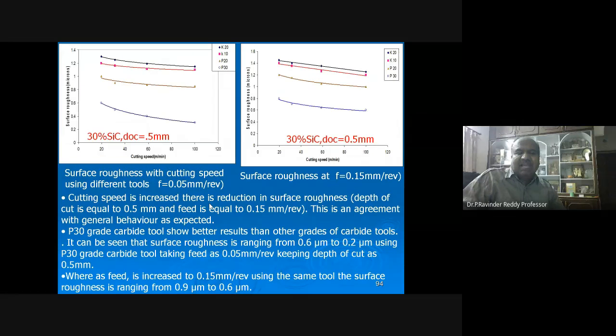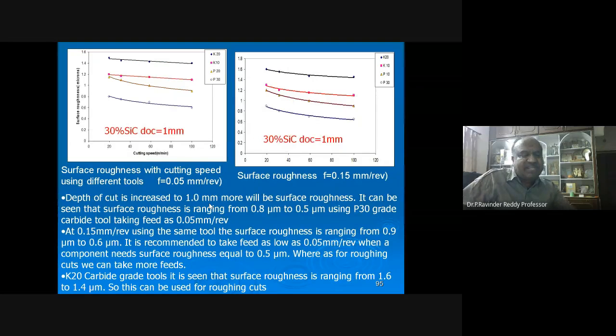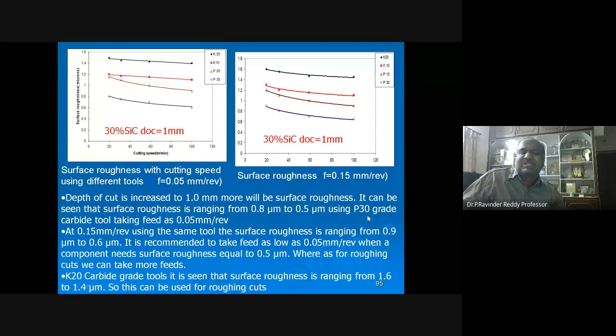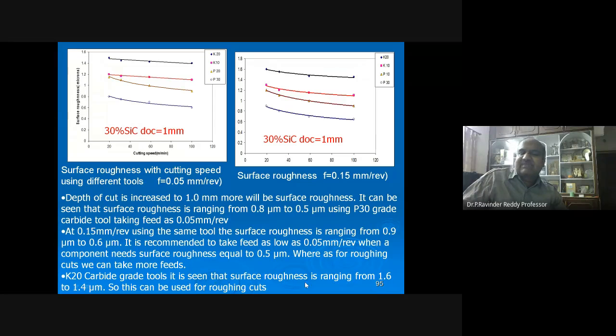So we have calculated at the different feed rates, keeping the feed rate constant and the depth of cut constant, all the parameters have been studied. As the depth of cut is increased to 1 mm, the surface roughness will be higher. It can be seen that the surface roughness ranges from 0.8 microns to 0.5 microns using the P30 grade carbide tool. At 0.15 mm per revolution using the same tool, the surface roughness ranges from 0.9 microns to 0.6 microns. With K20 carbide grade tools, it is seen that the surface roughness ranges between 1.6 and 1.4 microns.